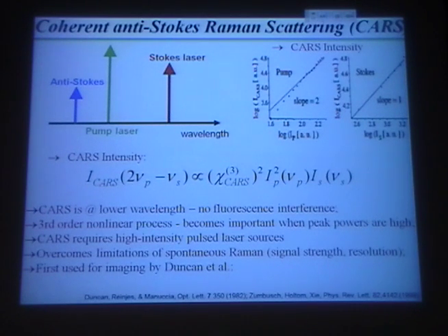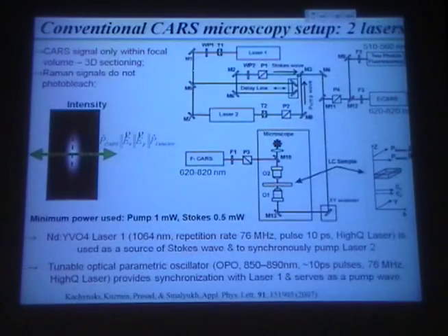Now, the big advantage of using CARS or SRS or multiphoton fluorescence, as I already mentioned, is that we can do excitation in the infrared part of the spectrum, but detect the light in the visible part of the spectrum, and this makes it easy to implement. At the same time, penetration of near-infrared light in scattering, highly birefringent media, as many of you know, is better than that of visible light, and this therefore provides important advantages as well.